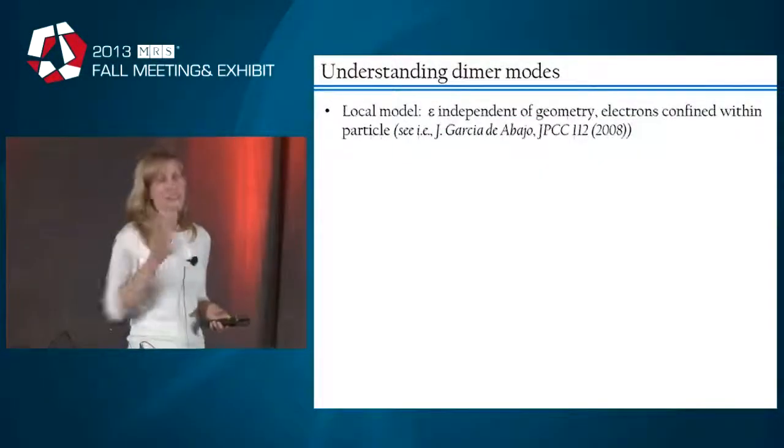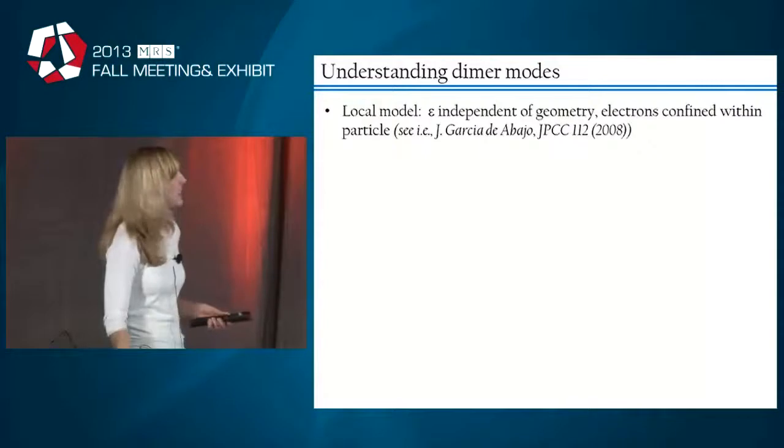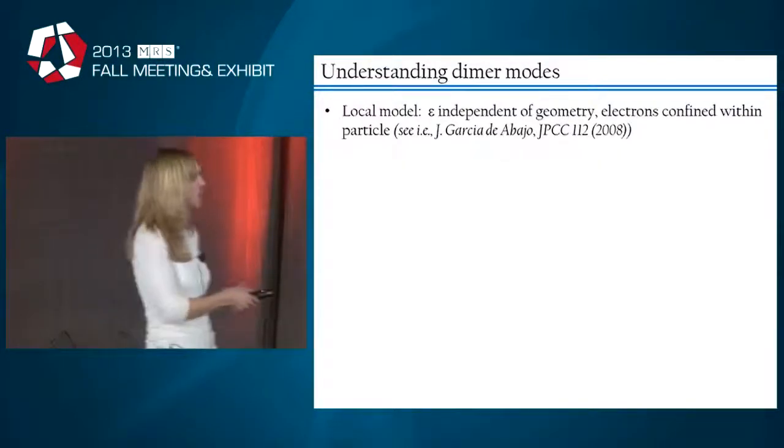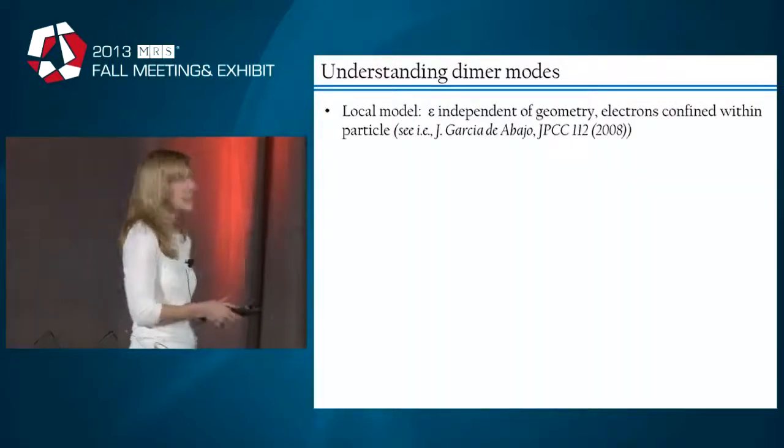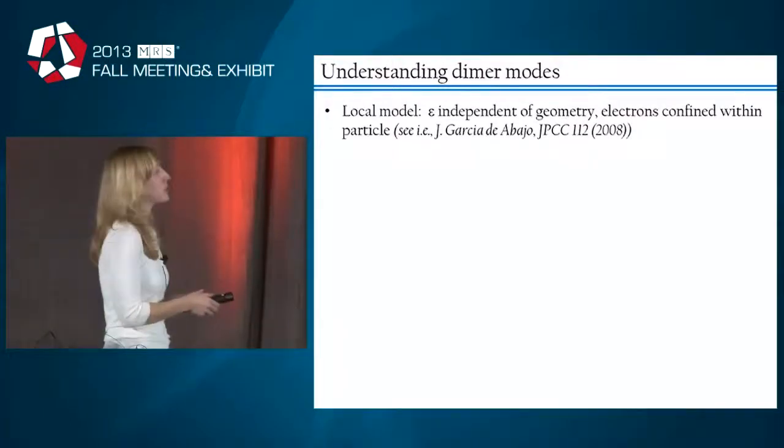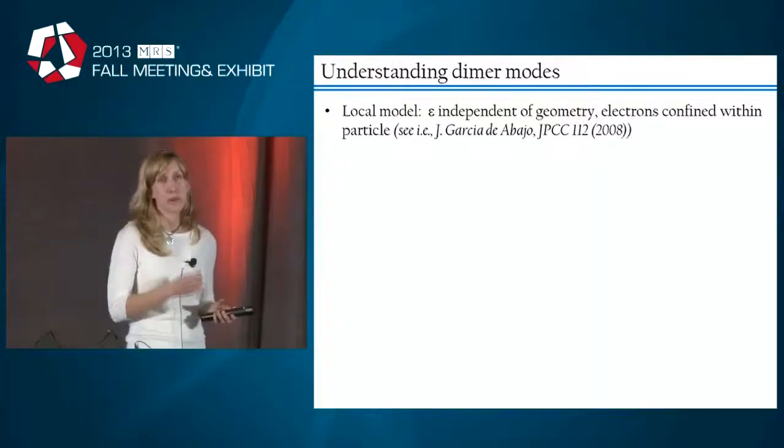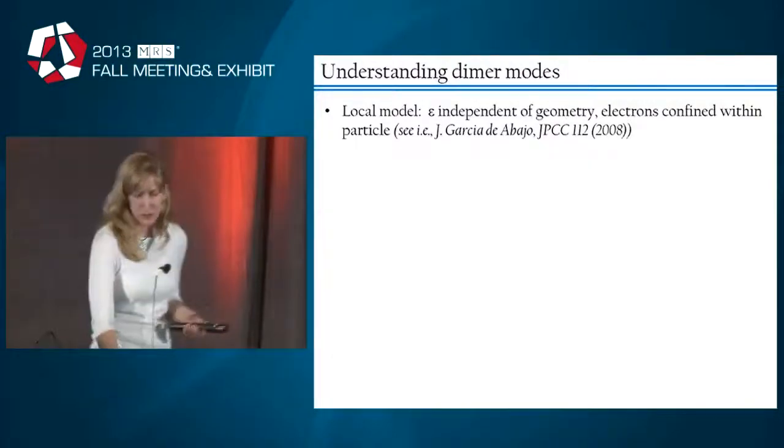So how do we understand these surface plasmon resonances? What you might do is consider a local model where the permittivity of the particle is basically independent of geometry. So you have a bulk permittivity, particularly since we have such large particles, and you assume that electrons are confined to the particle by essentially an infinite potential well.